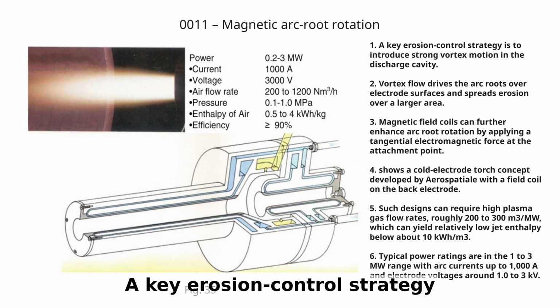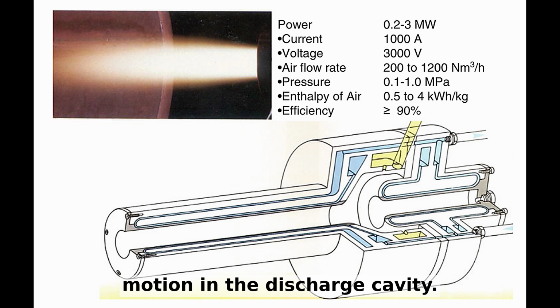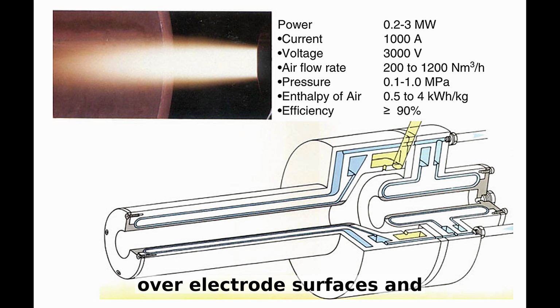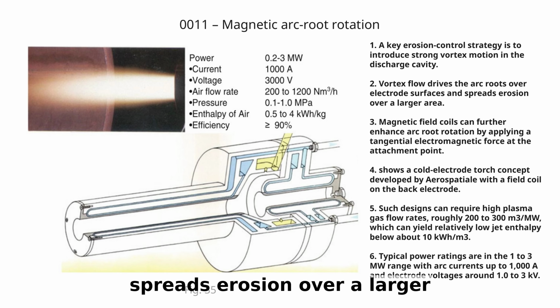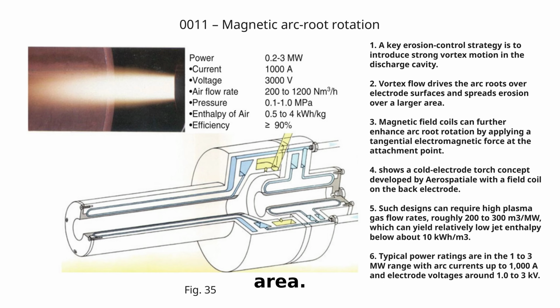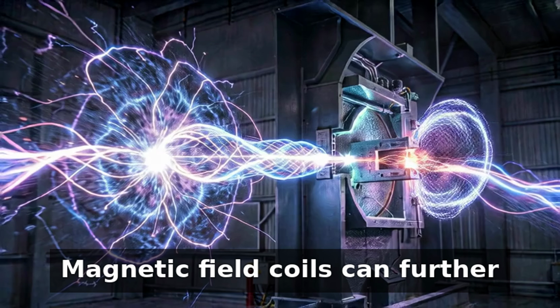A key erosion control strategy is to introduce strong vortex motion in the discharge cavity. Vortex flow drives the arc roots over electrode surfaces and spreads erosion over a larger area. Magnetic field coils can further enhance arc-root rotation by applying a tangential electromagnetic force at the attachment point.